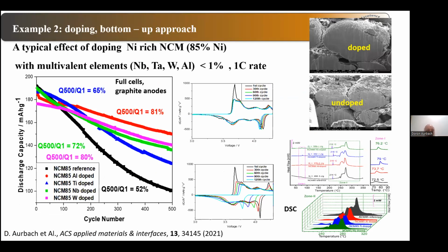Another option is doping with niobium, tantalum, tungsten, aluminum, and here we are using the so-called bottom-up approach. Upon the preparation, we mix the precursors, which contain lithium hydroxide and the oxides or hydroxide of the transition metal in the right stoichiometry. We also add 1% of oxide of the dopants, and with the heat treatment, we reach doping. Here you can see a cycling test in full cells versus graphite during several hundreds of cycles. The reference has pronounced capacity fading, and with doping, we stabilize the material.